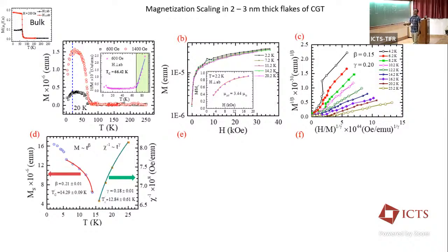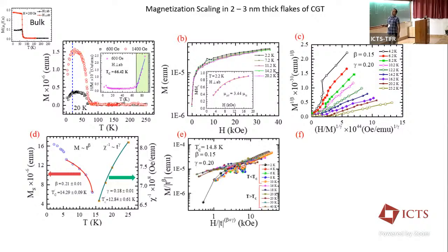And there is a critical transition which is sitting at around 12 Kelvin, and the critical parameters are beta equal to 0.21 and gamma equal to 0.18. If you fit these to the critical exponents, you will get the exponent values, and the exponent values around this transition now have completely changed. They have deviated from the 2D Ising-like behavior. They are no longer 2D Ising-like.